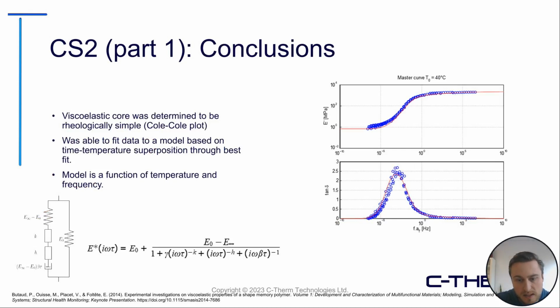So that concludes the DMA portion. What they were able to do with this viscoelastic data was show that the core was rheologically simple, so it followed the TTS method, and they could move forward with their modeling. They fit this raw data to a model shown below, which has springs, a damper, and some quasi-static components marked with K and H. I won't get too much into that since it exceeds what we're talking about today, but I wanted to at least highlight that.